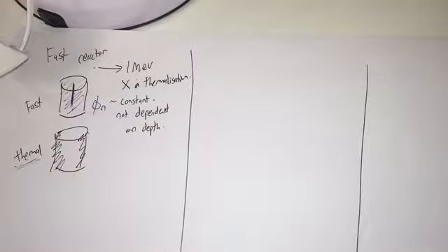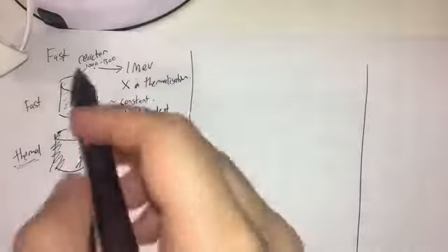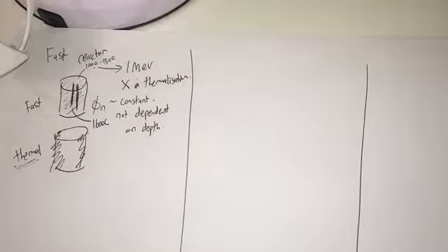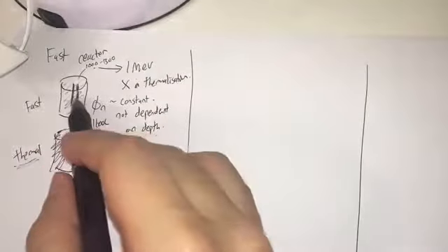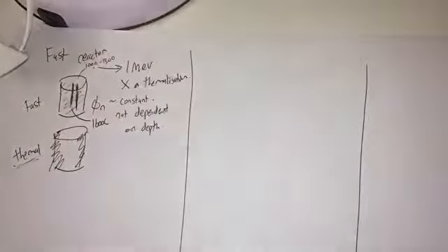So we are talking about a very steep temperature gradient. So steep that at the center of this pellet, temperature can reach as high as 1600 degrees C. And slightly outside, okay, we have a temperature slightly decreased, 1300 degrees C. So temperature will drop as it goes outside. But at the center the temperature is very high and the temperature gradient is also very high.